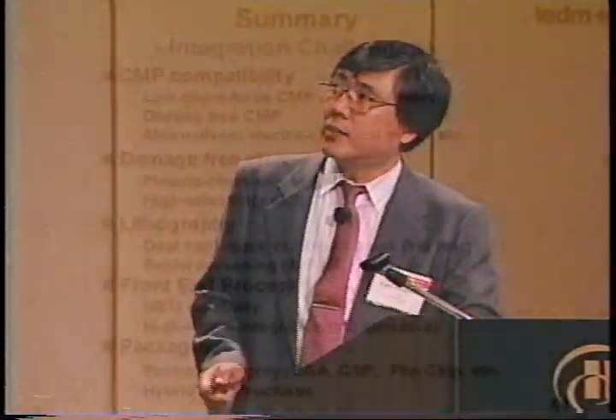And in that paper, they said additional layer solve the delamination of aluminum pad or porous low K. They are thick passivation onto low K film. In that case, the other is also a copper SiO2 dual damascene structure onto a copper low K process. By adopting these two approaches, the packaging failure was much improved. I'll summarize this section.